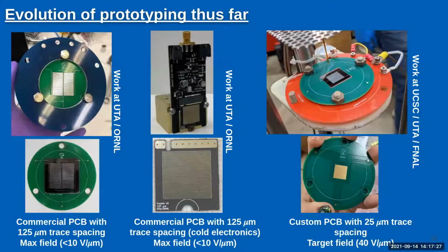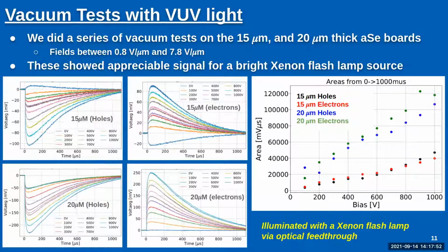In the last year, we've managed to go through three evolutions of prototypes, starting with these Snoopy boards on the left, moving to a smaller board that we could test for various temperature understandings, known as the cookie board, in the middle. And then on the right is an adaptation of the Snoopy board where we've gone down to extremely fine spacings, these 25 micrometer spacings, to target higher and higher fields on the selenium board. The first test we did once we had some selenium boards evaporated was to put them under VUV light in a vacuum.